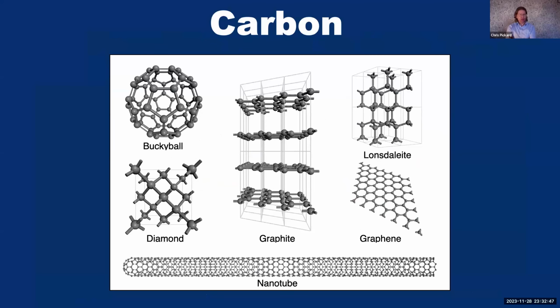Now, carbon's a very iconic element, given the very wide range of bonding that it can take up. The thermodynamically stable phases of carbon are graphite, which is the most stable phase under ambient conditions, and diamond, which becomes stable under elevated pressures. But there are other possible phases of carbon, for example, fullerenes, buckyballs, graphene, nanotubes, and other stackings of diamond, such as lonsdaleite, which is hexagonal diamond. And each of these metastable phases of carbon elicit great excitement and sometimes Nobel prizes.